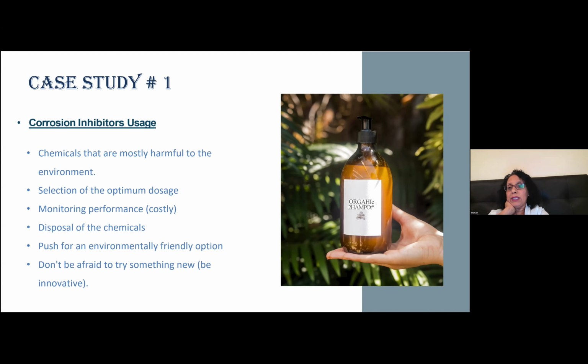And how would you do that? By taking regular samples and checking. So how do we do this? Let's say, we'll talk about pipeline, which is a common way of using corrosion inhibitor. You put your corrosion inhibitor in the pipeline stream, and this corrosion inhibitor is expected as a chemical to stick to the metal surface and protect it, and doesn't get the water to react with the metal surface. That's the idea of corrosion inhibitors.